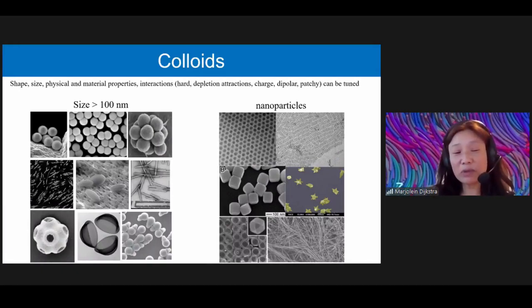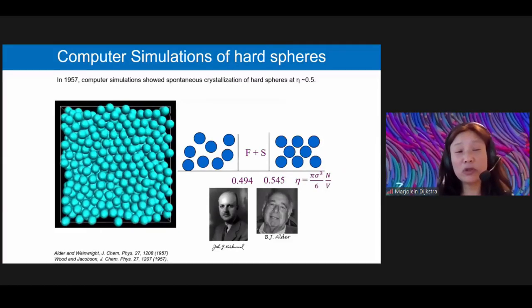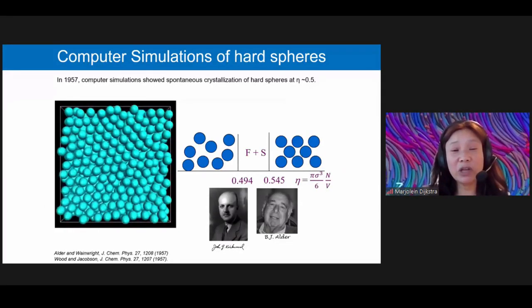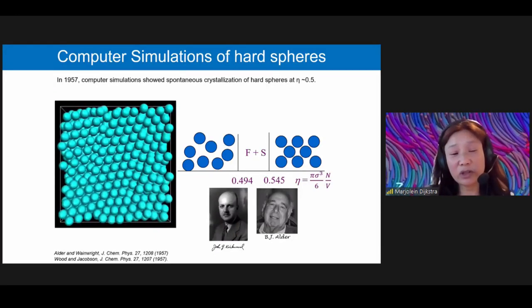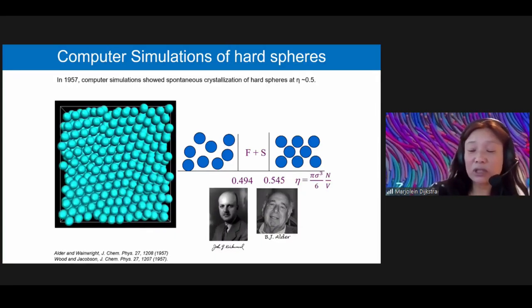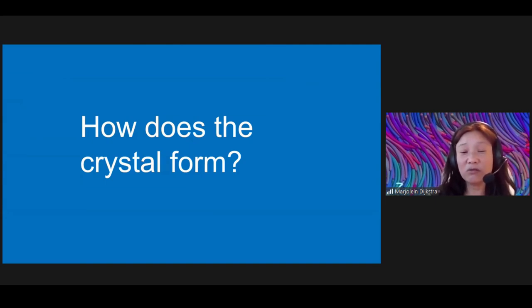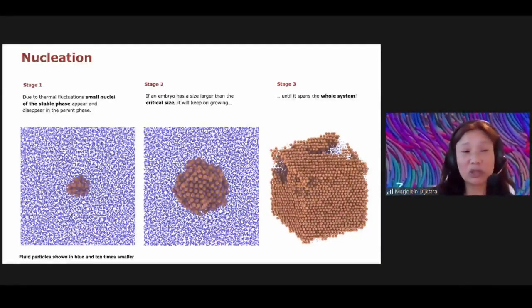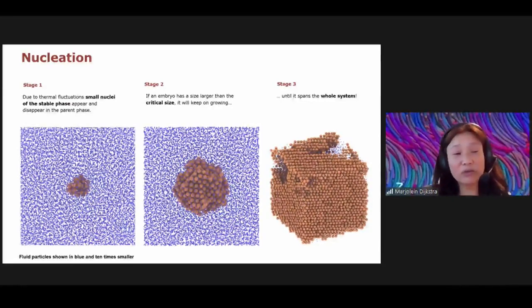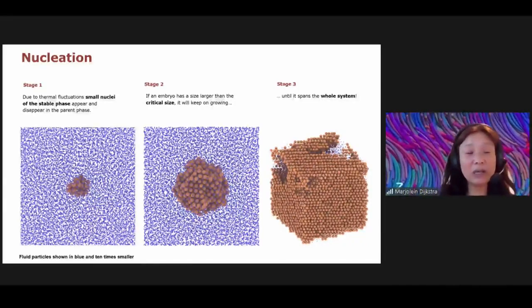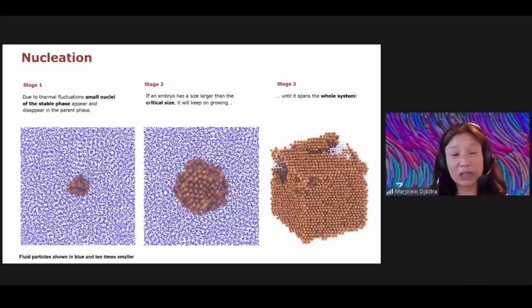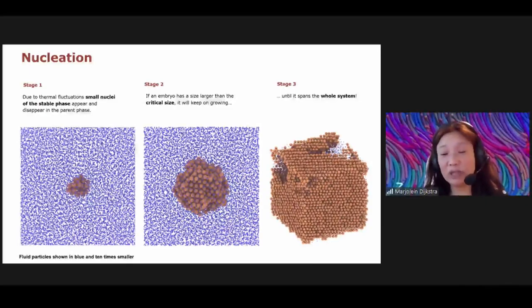And so if we go back to the simplest system, hard spheres, we already know from computer simulation in 1957 that such a system shows a spontaneous crystallization from a fluid phase towards the cubic crystal phase. And this was indeed verified also by colloidal experiments that were done by Pusey and Van Megen in 1986. Another question that one can ask is, how does such a crystal form out of a supersaturated fluid phase? And this brings me back to the process of nucleation. If you start with a supersaturated fluid phase, then small nuclei can appear of the stable phase. They appear, but also disappear until a nucleus is so big that it exceeds the critical size, and then it keeps on growing until it spans the whole system.